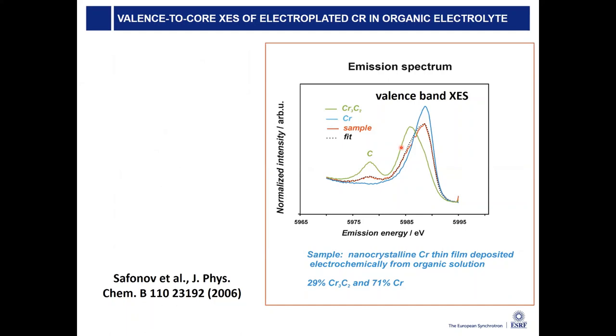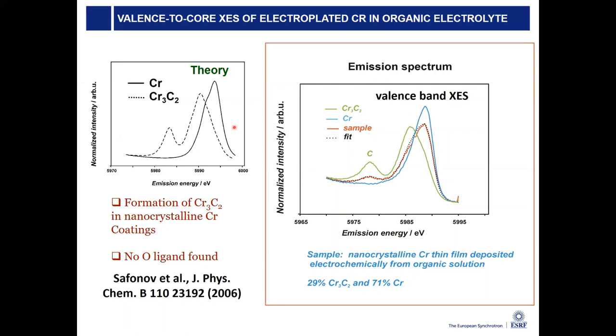And we use this, for example, to identify in electroplated samples to what extent I have metallic chromium or chromium carbide. You can calculate those spectra very nicely using the FEFF code, for example. Anybody familiar with the FEFF code? You can calculate the spectra, it comes out quite nicely, and you see the difference between metallic chromium and chromium carbide, just looking at the carbon 2s peak here in the X-ray emission data. Okay, so this is a very nice tool to identify your ligand environment.